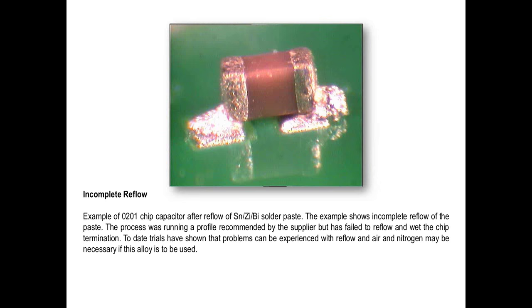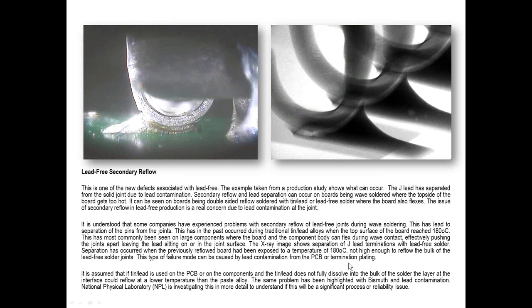Another example, again, early days of lead-free technology with very small passive parts. You can see this. And what we're using here is a tin zinc bismuth solder paste. You can use tin bismuth solder paste, and that's become quite popular for low temperature processing. And certainly my experience with this material, certainly with the tin zinc bismuth material, is that nitrogen really is the way to go. The tin bismuth materials can be used in an air environment, but when you're looking at very small parts, again, that can be a little bit of a struggle, as you see in this example.